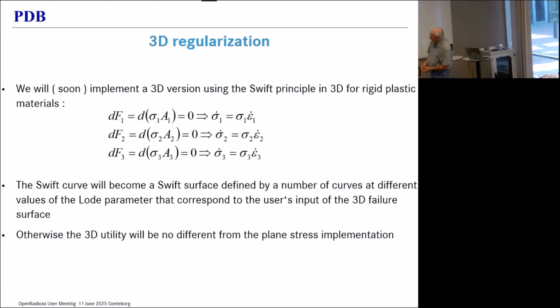That means that the Swift curve will become a Swift surface defined by a number of curves at different values of the Lode parameter. So we just have to generate one for every Lode parameter at which we have a failure curve, and then we can combine them one by one in exactly the same way as you just saw. So that's going to be, although the equations are somewhat more complicated, a pretty straightforward process.